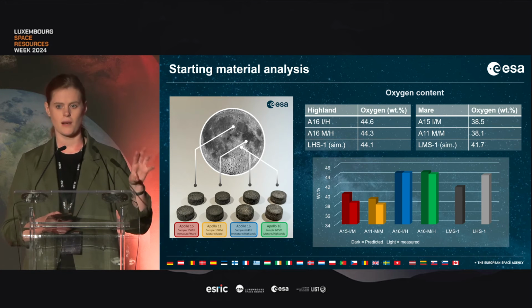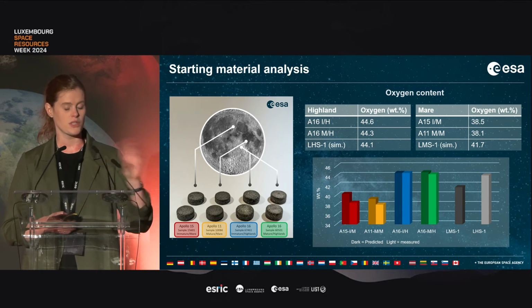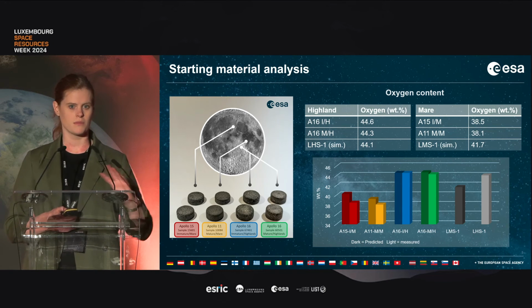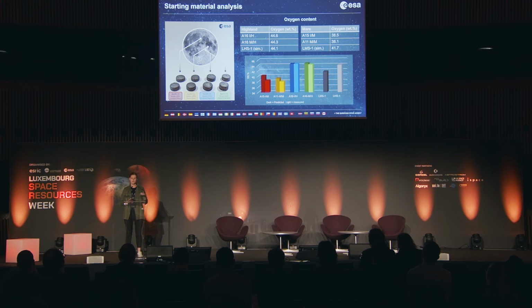So you can see here the dark bars on this chart is the kind of predicted value that you would get from the stoichiometry. And we can see that for the Mare material particularly, and also a little bit for the Highland mature material, we get a lower measured content, so we've got less oxygen available in that material.